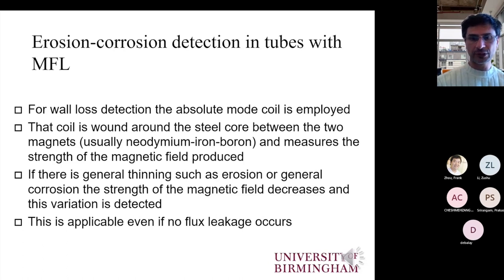Of course, apart from corrosion, we can also detect erosion. Of course, during the inspection itself, it may not be possible to differentiate between the two. So it depends on what the test piece is, whether we can recognize whether it's erosion, corrosion, or a combination of both, because we can have erosion-corrosion defects affecting certain components. And of course, with experience, this can be anticipated when we do the inspection. So we can anticipate certain types of defects due to previous knowledge that we have gained with time.